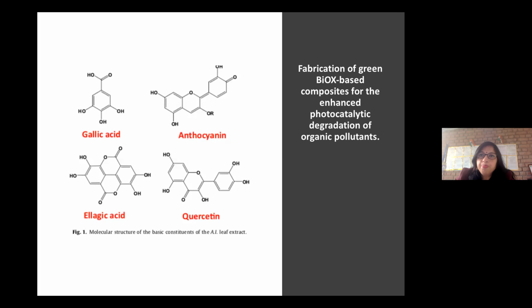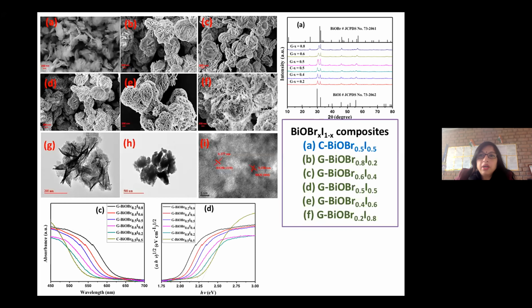Finally, not only bismuth oxyhalides were prepared here, but we also went on to see the composites, because if we can apply other methods which can enhance the photocatalytic activity, which can separate more electron hole pairs, that can give better results. So for that we took the next step, and prepared different composites of bismuth oxyhalides, bromides and iodides, in different ratios: 50-50, 80-20, 60-40, 40-60, and 20-80, and we gave the nomenclature accordingly.